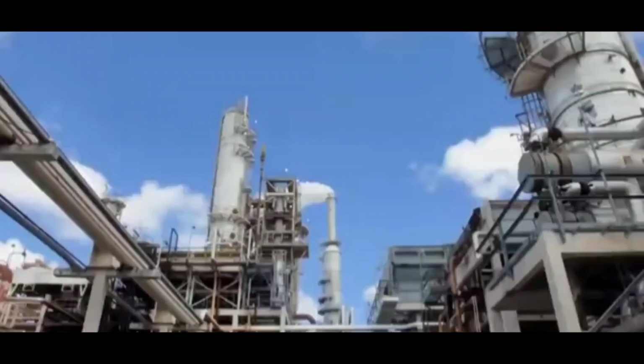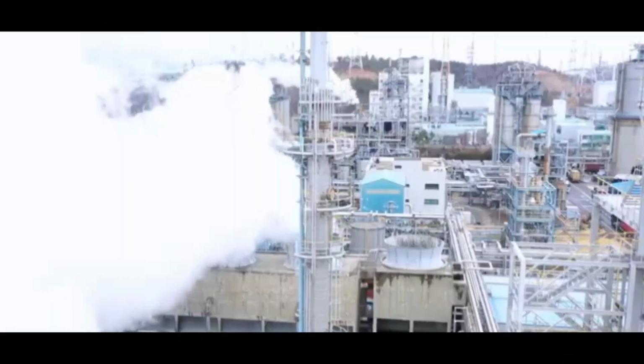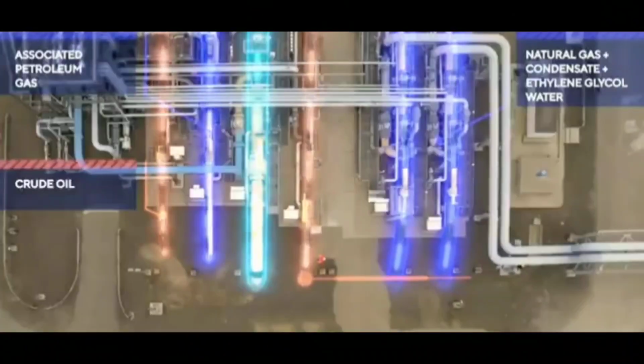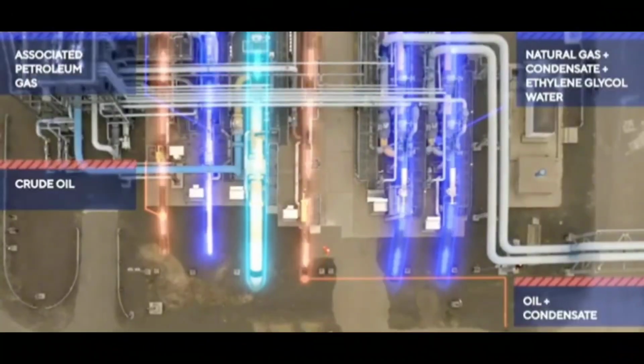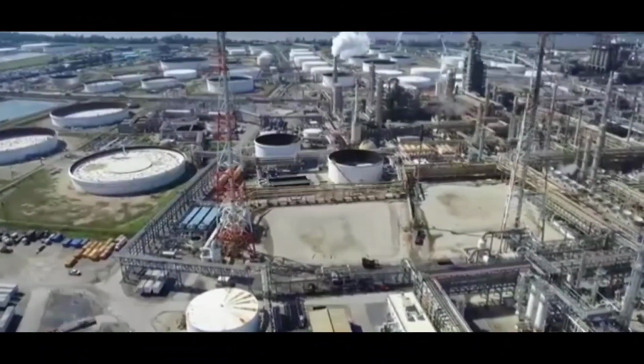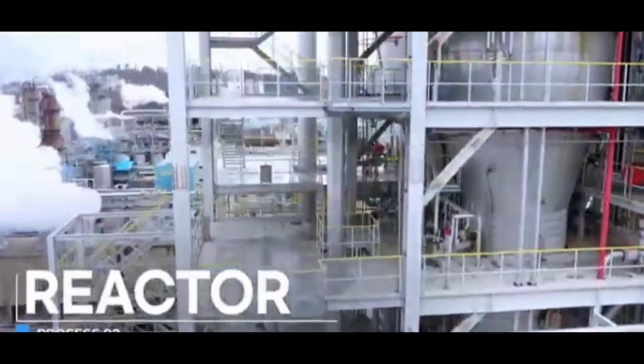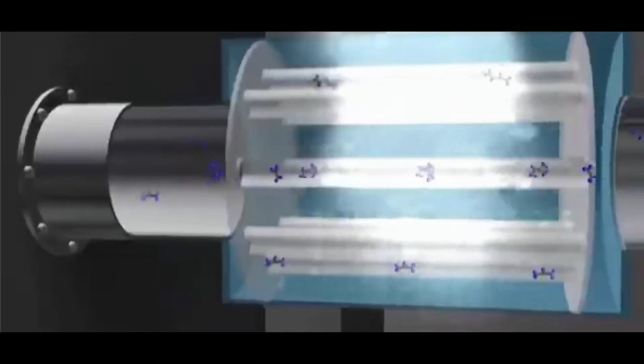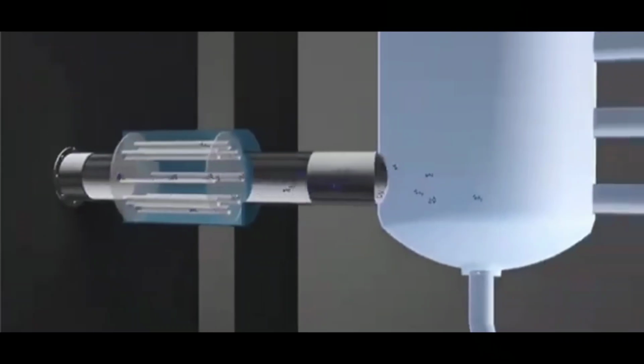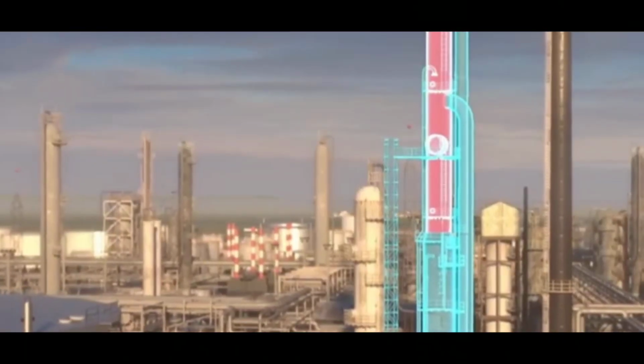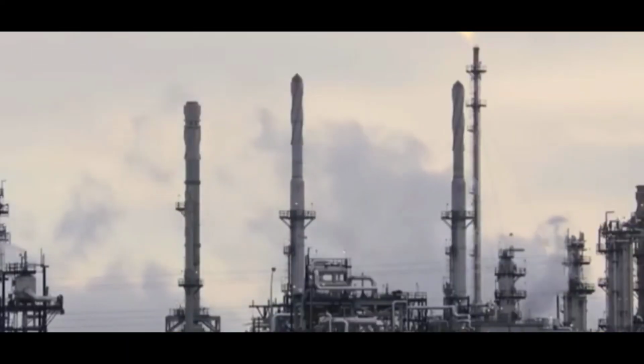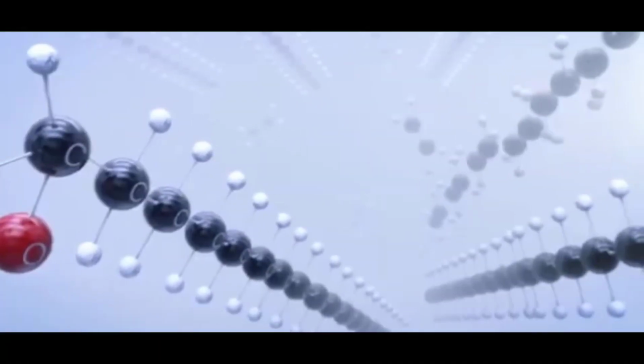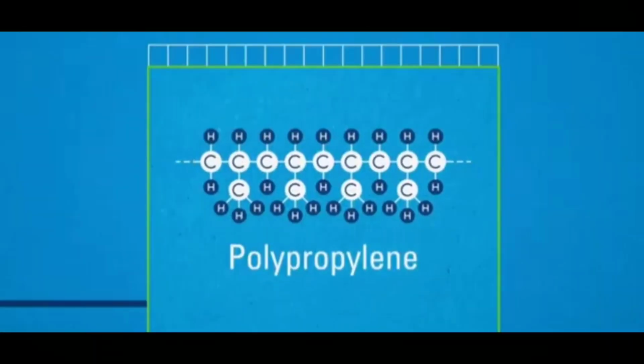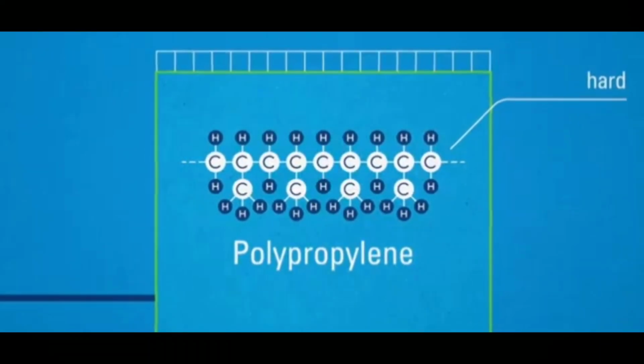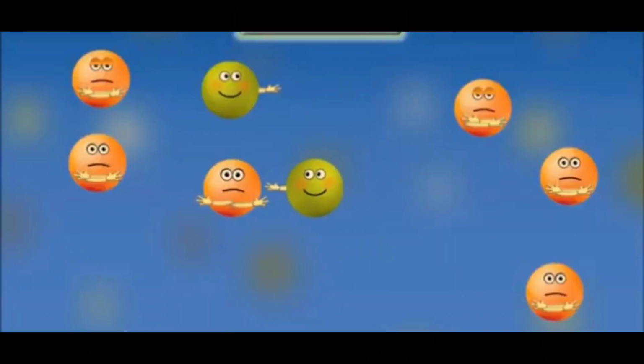When the final pallet of adhesive tape leaves the production line, upstream in the supply chain, a new cycle begins, as polypropylene pellets are once again created from petroleum and natural gas, marking the start of the material's next life. The journey begins inside a polymerization reactor, where gaseous propylene combines with a Ziegler-Natta catalyst under pressures of around 450 psi and temperatures exceeding 300 degrees Fahrenheit. Here, propylene molecules link together to form long polymer chains, producing polypropylene, PP, a plastic prized for its tensile strength and moisture resistance.